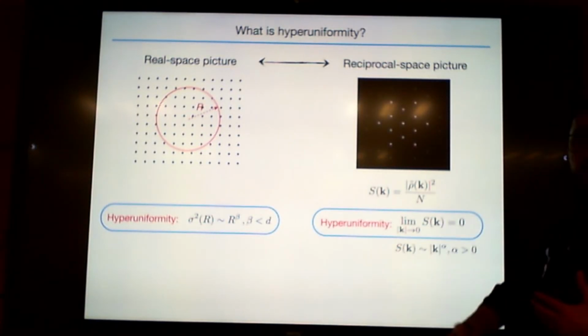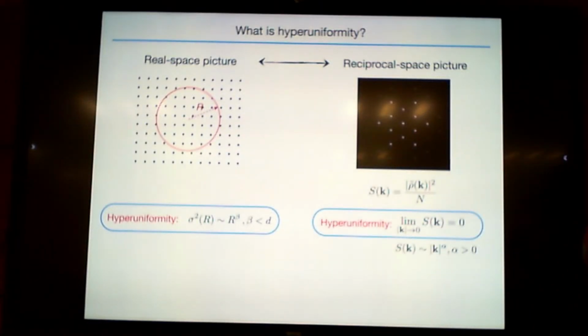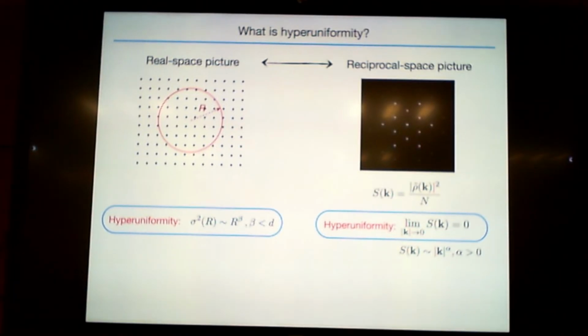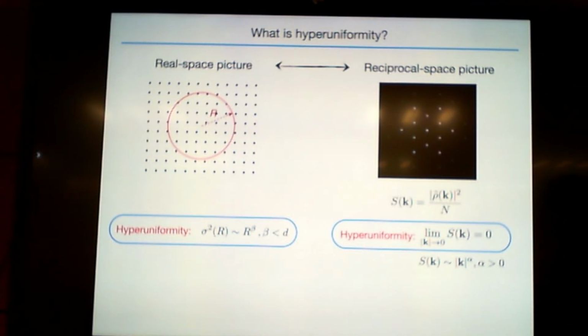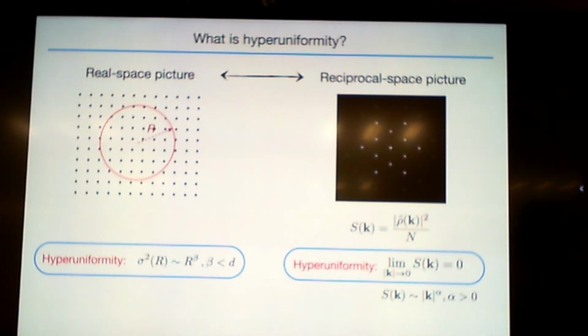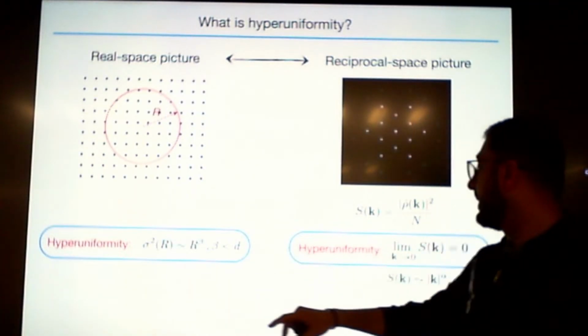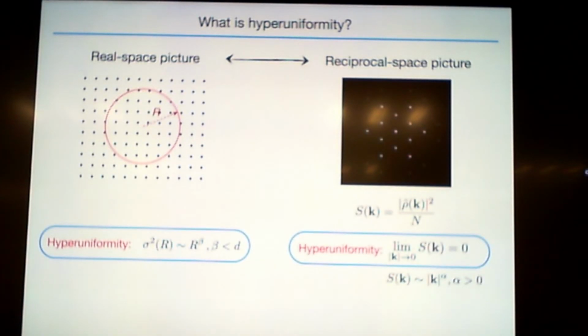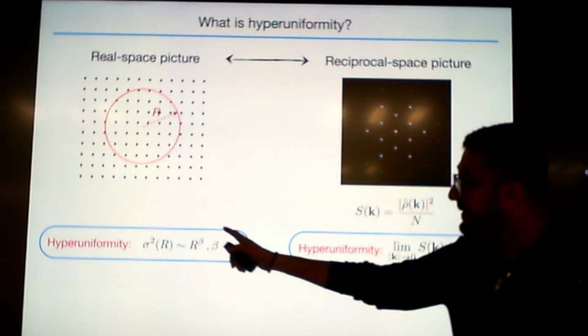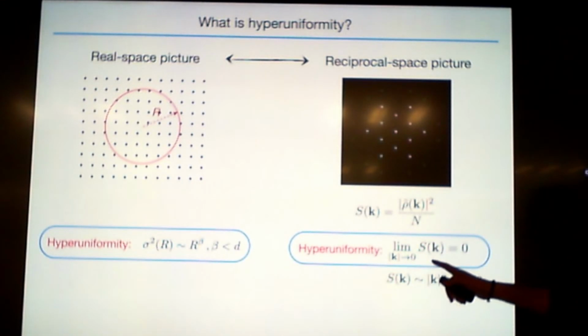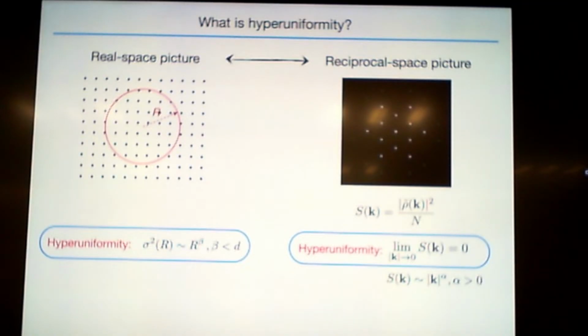This can be translated directly into Fourier space. What we need to do is to look at the Fourier transform, the structure factor, which is the density correlation in Fourier space, which is basically the Fourier transformation of the pair correlation function. It's the two-particle correlations in k space, in Fourier space. And in fact, there is a mathematically rigorous relation between sigma and the structure factor S. And this condition is fulfilled only if the structure factor goes to 0 as the wave number goes to 0. I will show you a few examples in a minute.